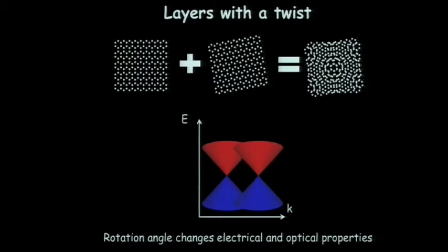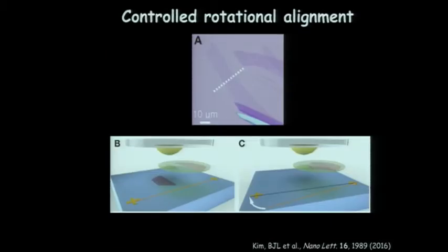So we were interested in looking here at a range of twist angles, and so we had developed this technique for basically making controllable rotations between the different layers. And so the idea here is to take a large piece of graphene here, and then we come down with our stamp to make this heterostructure, and we pick up just the left or the top half of it in this case. So you rip that off, you then have a small twist angle between them, and then you pick up the second half here.